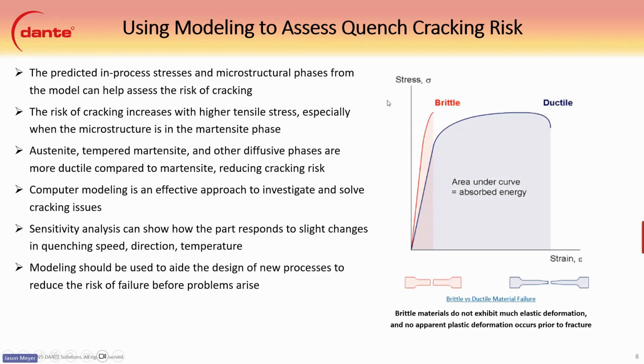So using modeling to assess the quench cracking risks, the predicted in-process stresses and microstructural phases from the model can help assess the risk of cracking. The risk of cracking increases with higher tensile stress, and especially when the microstructure is in the martensite phase. A lot of time when we talk about the cracks, they all happen usually in the as-quenched martensite phase. Austenite, tempered martensite, and other diffusive phases are more ductile compared to martensite, reducing the crack risk.